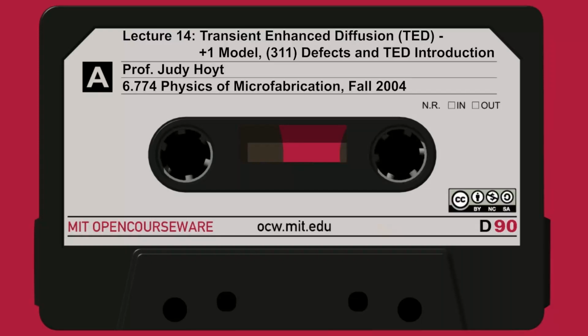After 10 minutes, I've grown up a little distance. At 15 minutes, you can see the amorphous crystal interface has progressed. And in fact, this is a linear growth rate you'll find. On the right-hand side, all the way on the right, at 20 minutes, there's only a small amorphous layer remaining. And if we were to go longer, the amorphous layer would entirely regrow, and you would have single crystal silicon completely in depth from the surface on down.